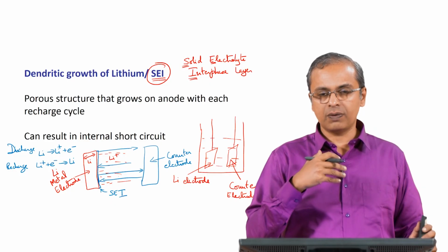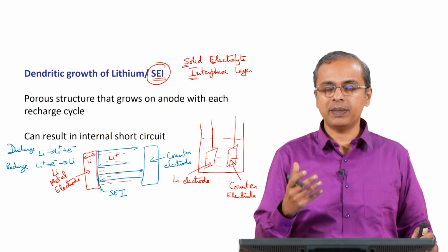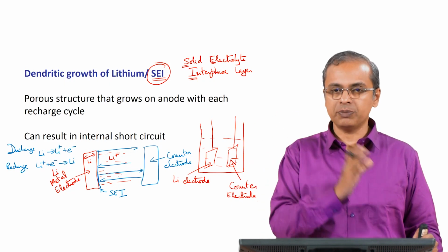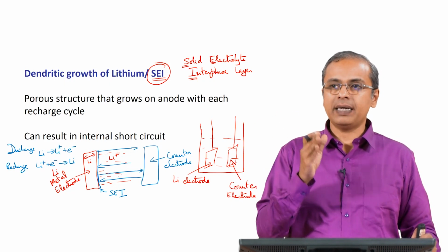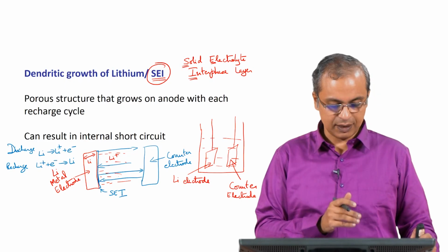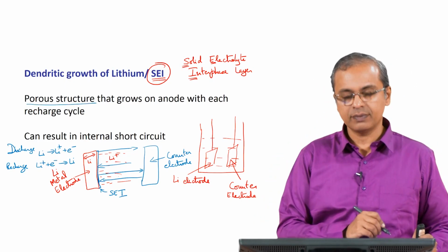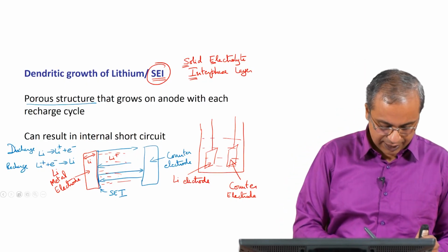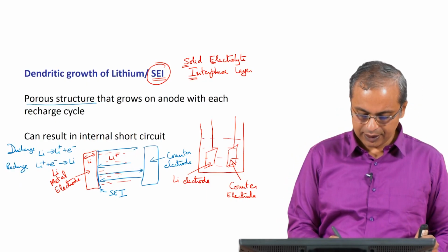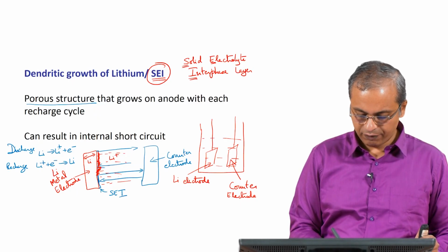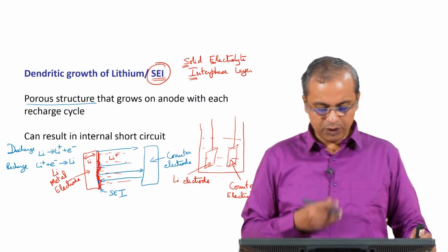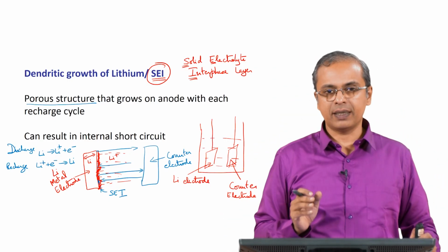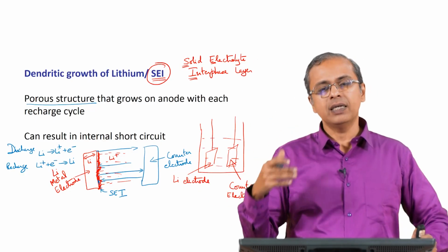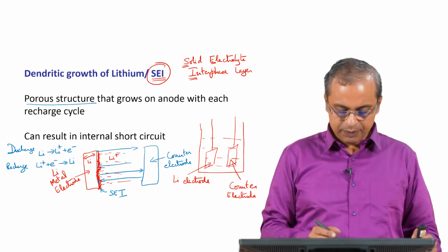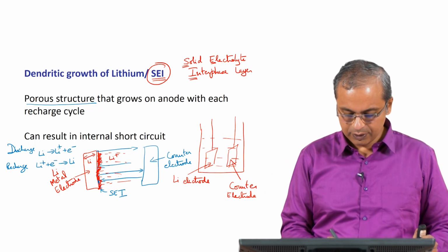Unfortunately, there is a huge amount of experimental evidence that shows that when lithium ion comes back and plates on the metal, it does not plate as a uniform flat structure. Instead, it forms a porous structure. So, what it means is you are having this lithium metal form like this, some kind of porous structure. With progressive cycling, and on top of it you form some solid electrolyte interface again, because now you have much larger area. So, this continues. With every cycle this becomes a more and more porous structure that is continuously growing.